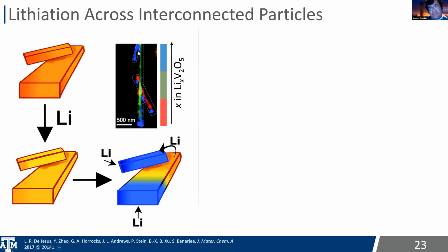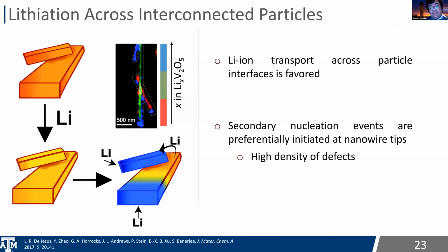The tips of the wires tend to be blue, but then you see these large scale heterogeneities, especially at the interfaces where they connect. And this is again a beautiful paper coming out from B.-X. Xu's group, which will look at some of the across grain boundary transport and how that results in local depletion at grain boundaries. And so essentially, the takeaway message is that these atomistic diffusion limitations resulting from small polarons, resulting from these electronic structure peculiarities, have some real consequences in single particles, in ensembles of particles, and then at electrodes.